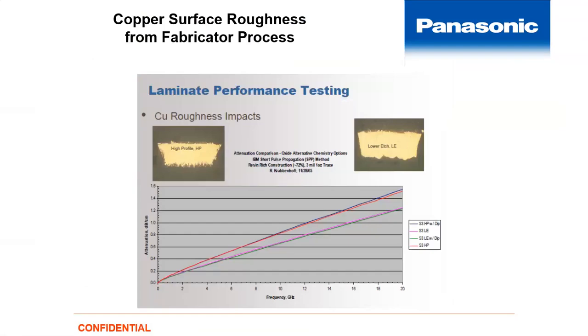Same thing with the oxides. So over the years, the oxides have had the primary purpose of bond, but now not only does it need to have a better bond, it also has to be able to minimize the loss, because all the good things we're doing, the extra money that we're spending on the high-performance foils, can be lost with having an oxide that doesn't perform. Here we've got two different oxides, so we're showing the high profile is the one that has the most